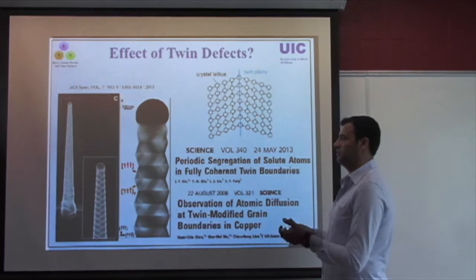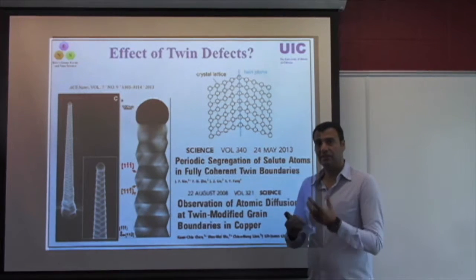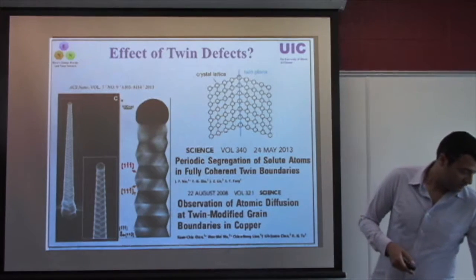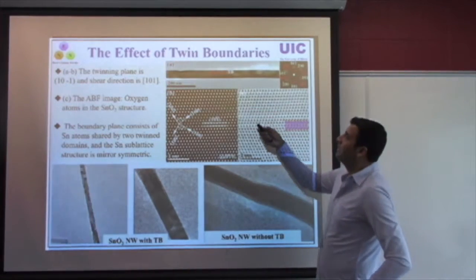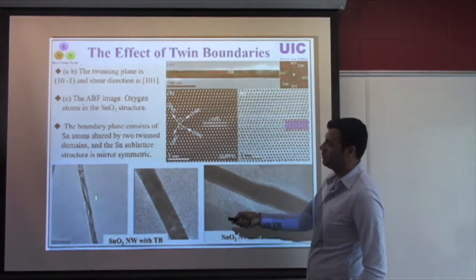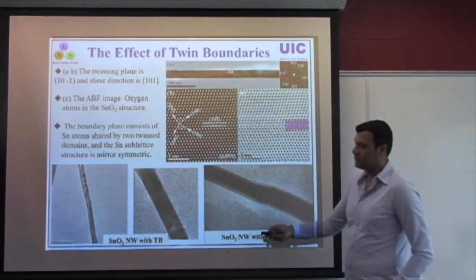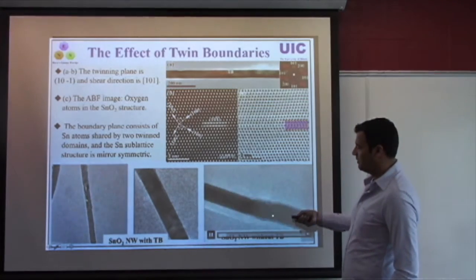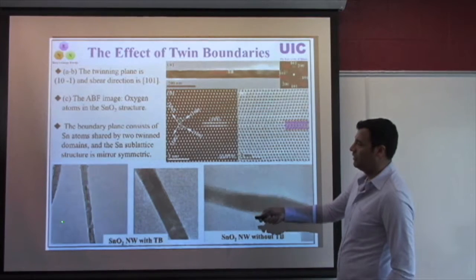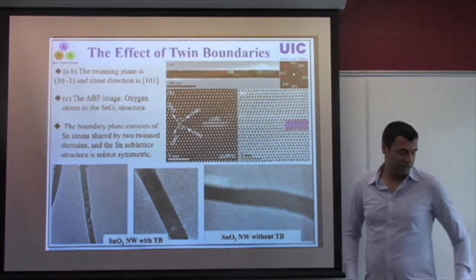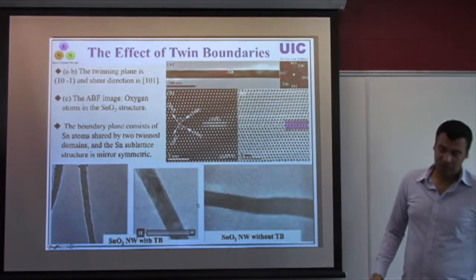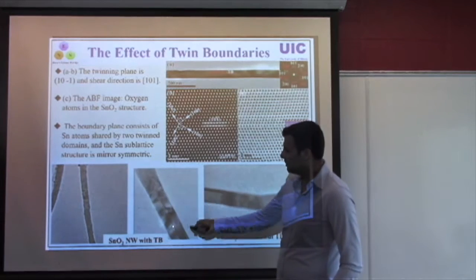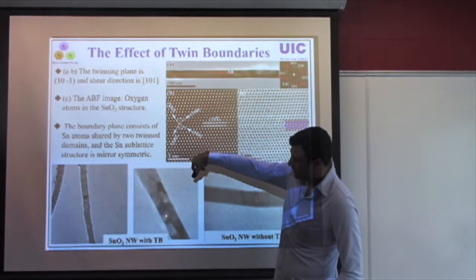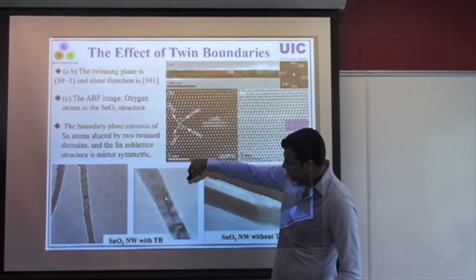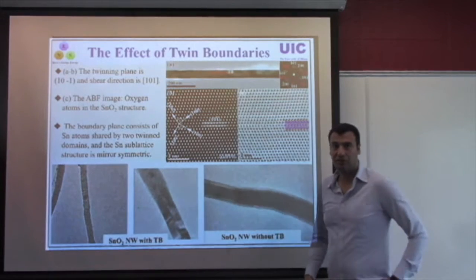So now, going to nanomaterials and nanoscale systems, understanding how defects interplay with the transport of ions is important. In particular, our team has been looking into twin boundaries, and this is an example of a nanowire which has a twin boundary, which shows quite distinct behavior compared to a case where we don't have any twin boundary in the sample, and we can see that the electrode behavior is very different in these two cases. If you zoom in a little bit more, this is an area where you have a twin boundary, and lithium is transporting through the sample, through this nanowire, mostly along this green twin boundary, and then propagating to the rest of the crystal.